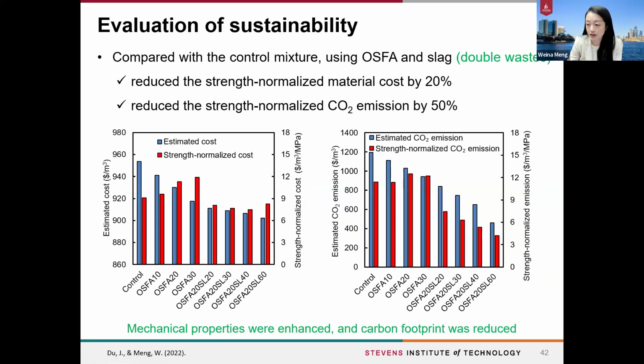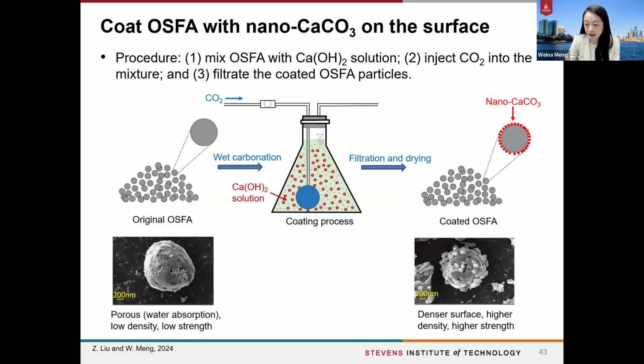So in terms of sustainability, as we use two types of waste materials in the system, we could reduce the strength normalized materials cost by 20% and reduce the strength normalized CO2 emission by 50%. As you can see here, the maximum OSFA we can use in this specific study is 20% without mitigating the strengths. To further improve the utilization rate of such waste materials, we're thinking to strengthen these porous structures with nano calcium carbonate. To create this calcium carbonate, we use a CO2 sequestration technology where we directly inject the CO2 into the calcium hydroxide rich solution. This solution was prepared with the OSFA, so we can coat the surface of the OSFA with the nano calcium carbonate. With that, we could significantly increase the utilization rate.